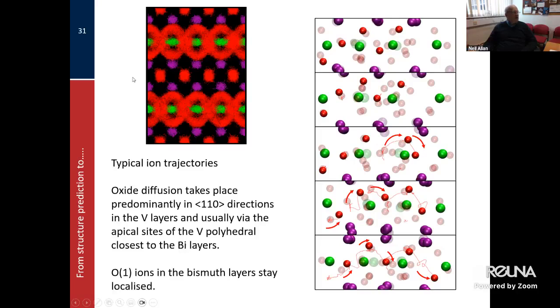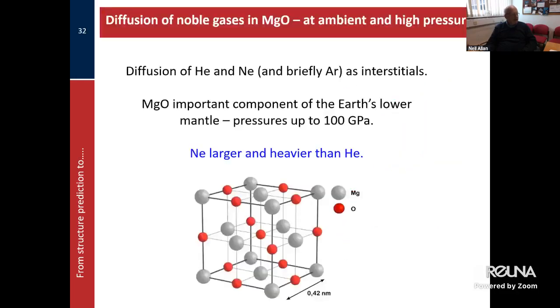And but the oxygens within the bismuth layers, the one that I predicted would be important, aren't important at all. What I'm pleased about is that I have seen a preprint, but I don't think it's come out yet, of a very exhaustive study of this system recently, which is a combined neutron study, X-ray diffraction study, very detailed experimental analysis, more than anything done in the past, which I'm happy to say gives results all consistent with our model. So these days, our calculations are able to really reveal useful, reliable information about really very complicated systems.